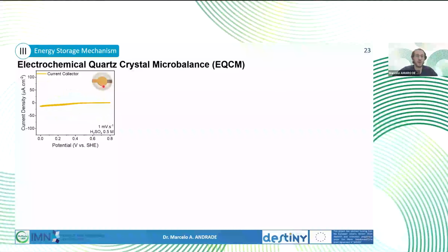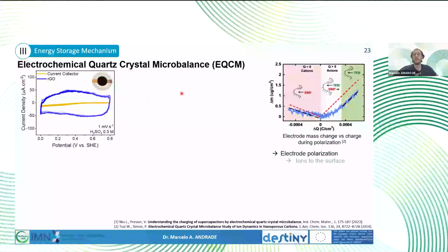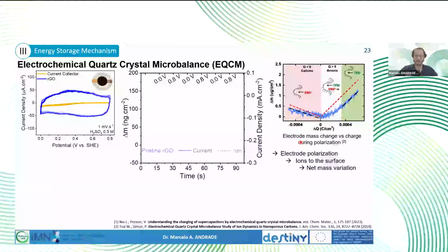First, it was pure gold, and we cannot see an electrochemical response for that. Once it's coated with RGO, we see the RGO envelope as expected. And also, just to understand what to expect from the EQCM, we expect a mass change with the polarization of the electrode. So when we polarize positively, we expect the anions to come to the surface and a very pronounced mass increase. Once we polarize the electrode negatively, it's the other way around. We expect the cations to come, so a net mass variation.